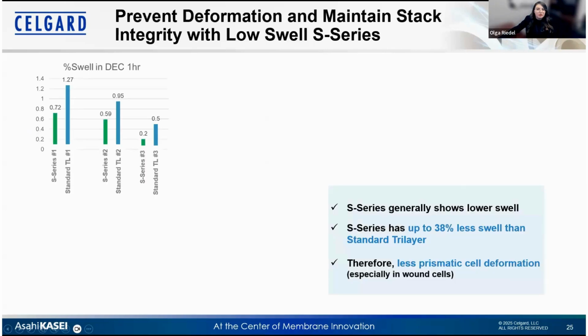Here's an actual example of the swelling in percentage. The separators were immersed in DEC carbonate for 1 hour and we afterwards measured the swelling. So compared to a standard trilayer, the S series actually shows a lower swelling, by as much as up to 38% reduction in swelling.